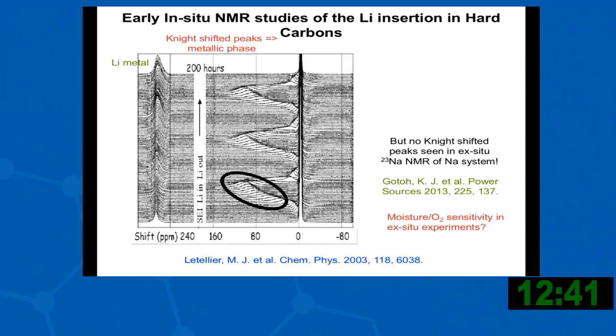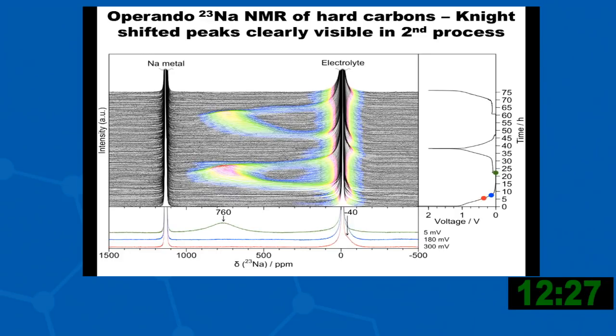And what was interesting was in the initial NMR studies of these materials that were done ex situ, in the sodium form, they didn't see any of this large shifted peak, and so they proposed the mechanism was very different. So we repeated this, and when we did it in situ, we were able to get rid of the problems due to the moisture sensitivity and air sensitivity, and you can really see very beautifully these large shifts going backwards and forwards in this sloping region. So the mechanism for lithium intercalation and sodium intercalation in a hard carbon is very similar.